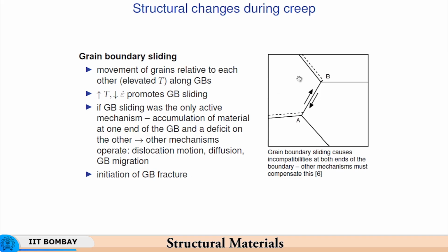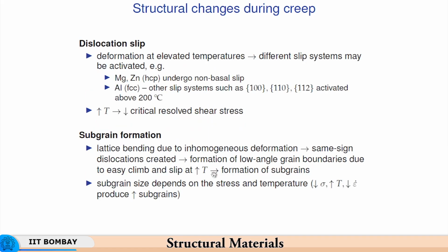temperature rises. The interior of the crystal turns out to be stronger. In fact, it also softens, as we have seen there. It also softens because of dislocation slip becoming easier and subgrain formation becoming easier, but because the grain boundaries soften faster, you will find that the grain boundary sliding is something that starts taking place, due to which the strain in the grain tends to reduce slightly. Strain due to grain boundary sliding, and this strain has to be accommodated by the process of diffusion, which is fairly slow.